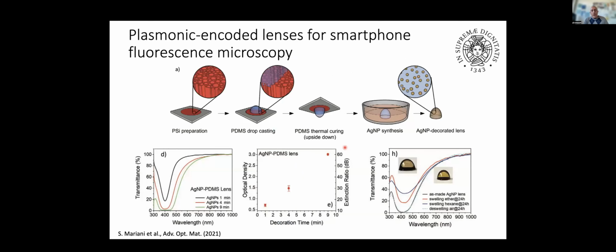We can do the same process, but then we can coat the lens by just putting it into a solution of metal salt like silver fluoride, and then the lens is coated with silver nanoparticles. You can do the same with gold nanoparticles or whatever. And this means that you also integrate on the lens surface a plasmonic filter that again cuts off the light at some specific wavelength, depending on the plasmonic resonance of your nanoparticles.